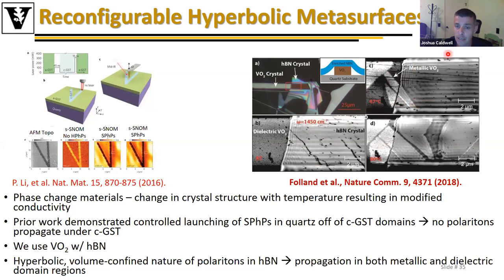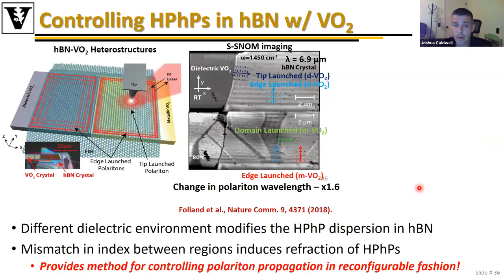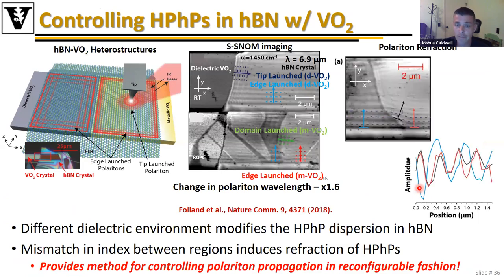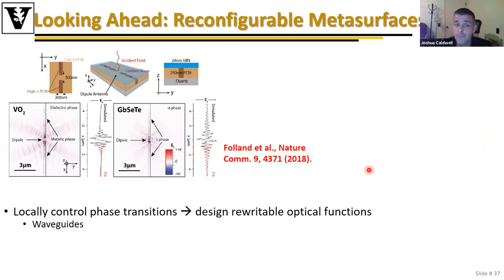And you can see that both in the boron nitride over the dielectric and metallic domains, you can support these polaritonic modes, but now they have different wavelengths and therefore different momenta, right? And so one of the interesting things that comes out of that is if I launch a mode in the dielectric regime, it comes to this interface. Because of the momentum mismatch between the two modes, it has to refract. And thus, this refraction enables us to use standard optical concepts used in the far field, but now on chip,